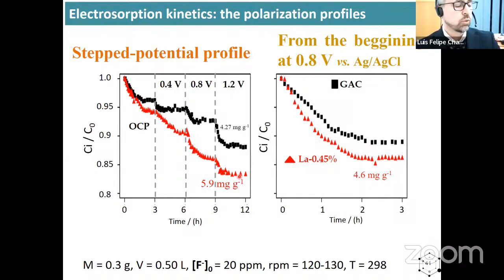When compared between samples, the effect of the anodic polarization on the removal capacities is marked, with a significant increase in the fluoride removal. And when the adsorbent electrode was polarized from the beginning, as I mentioned, with no previous step of conventional adsorption, the adsorption capacity for the modified material was lower than in this case.